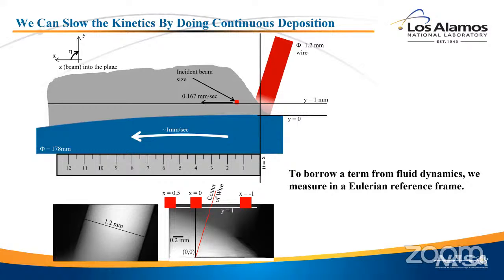Point is, when we did these measurements, our detector wasn't fast enough. So we had to come up with a way to slow down the kinetics. So it's two things we did. Instead of just depositing a point of material and then turning the welder off so it cooled very quickly, we rotate that wheel and we deposit a line of material, doing actual additive manufacture, if you want to look at it that way.